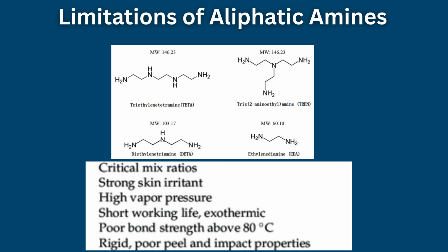Additionally, curing reactions involving large volumes of adhesive can generate significant exothermic heat. In thick sections, this heat buildup may lead to thermal degradation of the resin. As a result, batch sizes and bond line thicknesses must often be controlled to avoid excessive temperature rise.